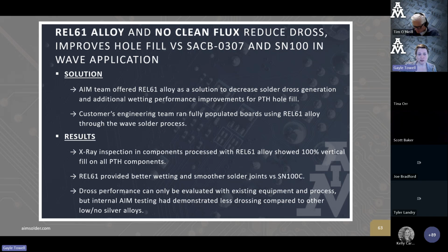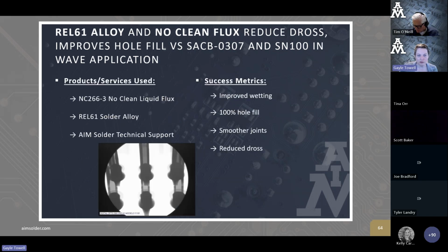In the end result, the X-ray inspection showed REL61 gave 100% vertical fill on all the through-hole components, better wetting, and smoother looking joints than the SN100C. And dross performance is tricky because it really depends on the conditions of your test. It's not something you can just quantify across all situations. But we happen to know from our internal testing that it tends to dross less. So again, they got improved wetting, perfect hole fill, smoother joints, and reduced dross in this application.